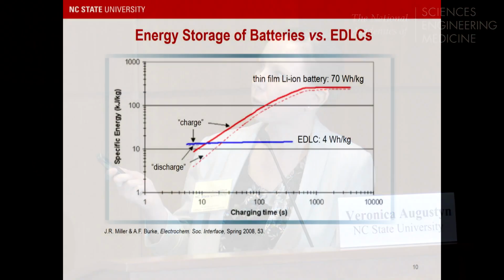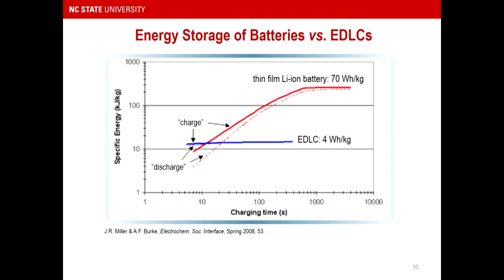Here's another comparison showing that at timescales of about 10 minutes or slower, lithium-ion batteries can do a pretty good job of maintaining their energy density. But as you push them to faster and faster timescales, not only does that energy density decrease, but you have the separation between the charge and discharge, the hysteresis or the energy inefficiency gets larger, versus the double-layer capacitor, which has the more modest energy density, maintains it almost ideally, and at some point there's a crossover between the two.